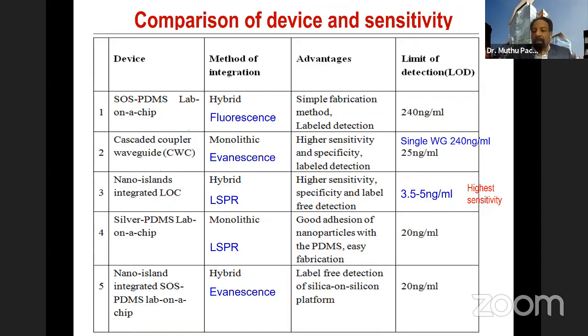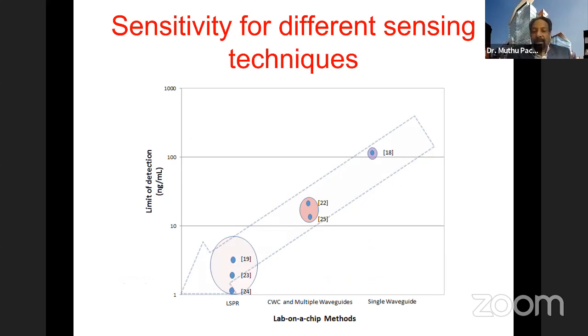If you look at the comparisons of all this, the various optical systems, fluorescence, evanescence, LSPR, all gave different kinds of sensitivity and complexity and simplicity. So we find LSPR seems to be the most sensitive out of all of these. In comparison, LSPR seems to be highly sensitive compared to evanescence as well as absorption-based or fluorescence-based. And we also found that much more sensitivity is possible when you go in a monolithic way.